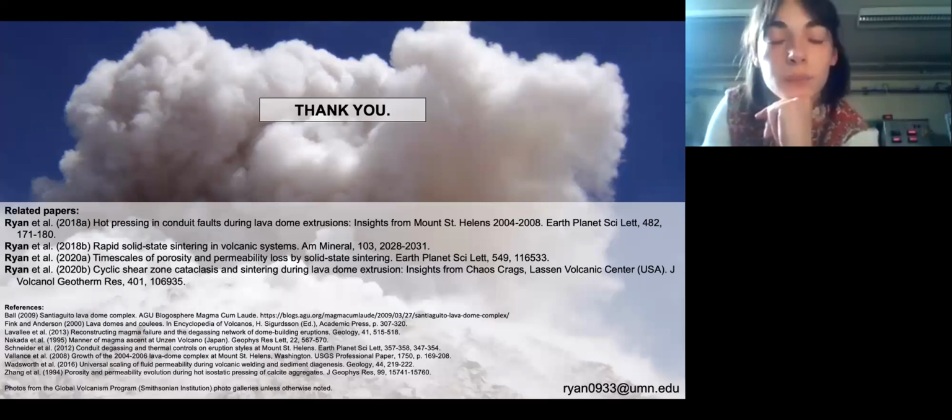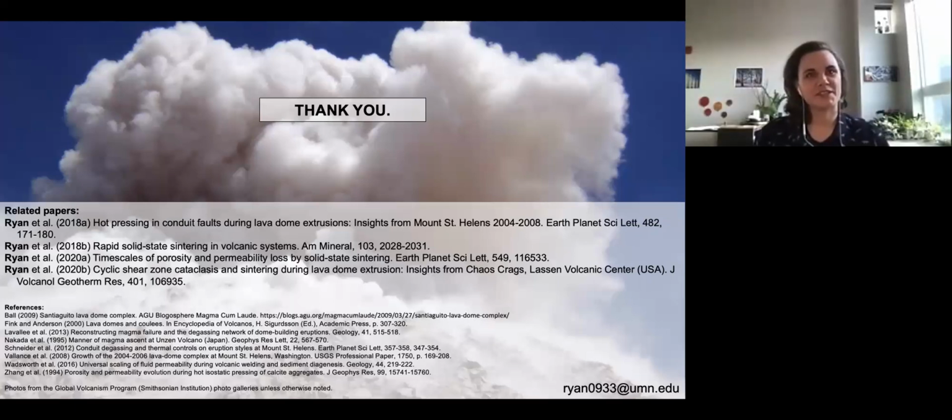Yeah. In these materials, there is no glass present, and we're below the solidus where you would expect the materials to begin to melt. So I'm confident in saying the materials that I've looked at here are not experiencing any sort of viscous sintering. But were melt to be present, you can imagine, as you know, because you work on this, the time scale of sintering will be so much faster.